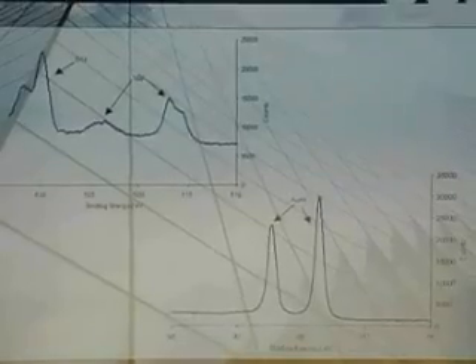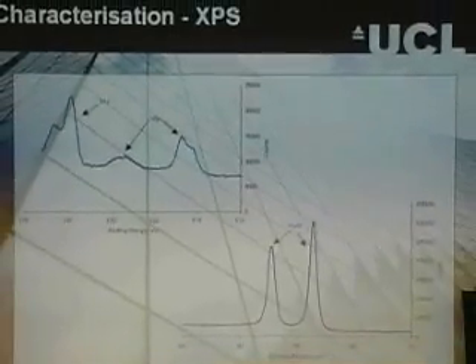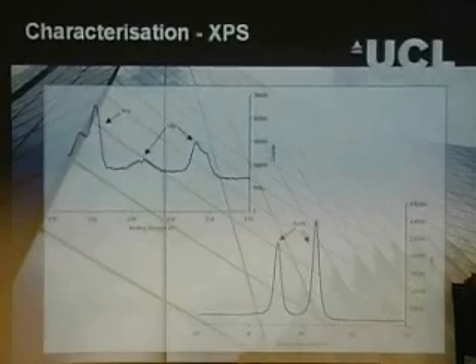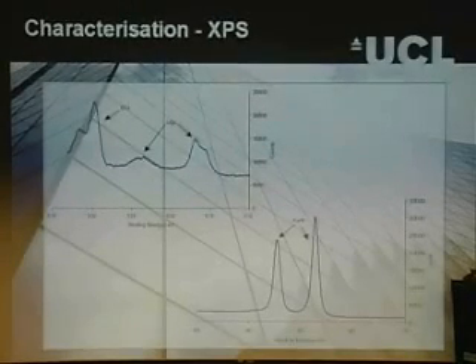If we look at some X-ray photoelectron spectroscopy of the surface, we again see that we've got one nice gold environment, very symmetrical peaks, which tells us that basically the gold is just there as crystallites. There's no doping as such. If we look at the vanadium and oxygen environments, we see that there's more than one environment there. And as this is the surface, we come to expect this. We expect there not only to be vanadium in a +4 environment for VO2, but some extra oxidation to V2O5, and that's reflected there. And this is very common and well known.